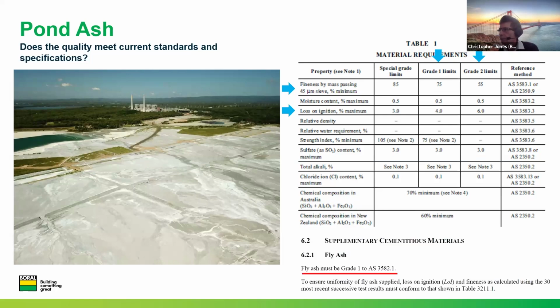The barrier to grade 2 ash is that many specifications call up grade 1 ash. This extract on the bottom right is from a Transport for New South Wales specification, and it states that grade 1 ash must be used. So we may need to have some conversations with specifiers and suggest that the specification should be based on the performance of the concrete, and if we can achieve that with grade 2 ash, then it should comply.